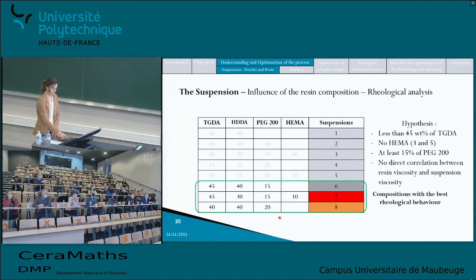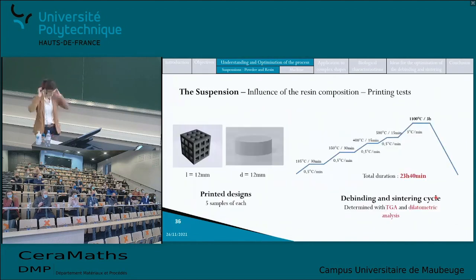So I pursued the experiment with the printing tests. I selected 2 different designs, a cube with holes and pellets with a diameter of 12 millimeters. I printed 5 samples of each design and evaluated them. I built the debinding and sintering cycle based on TGA analysis and dilatometric analysis. So first, I observed the printed pellets with a 3D microscope. And what we can see here quickly is that not all the suspensions lead to the same sample.